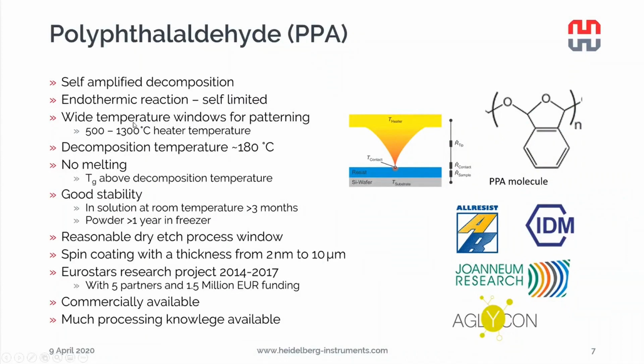The upper temperature limit is basically another phase change that we have to consider, and this is the melting point of the heater. At about 1400 degrees, silicon will melt, and we will basically destroy our heater if we increase the temperature even more. But this gives us quite a nice temperature window to play with. And in the end, this temperature means how much heat do we put into the sample. The higher we go with the temperature, the more heat flow we get into the substrate, and we can control quite nicely how much volume we remove with a single indentation.